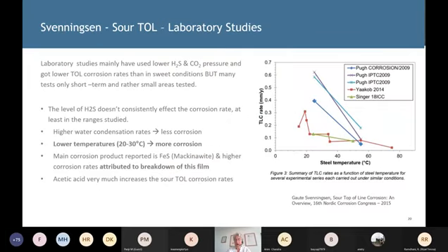I want to point out there's an area where we really don't know too much at all, and that's top-line corrosion in sour systems. Now, this paper by Svenningsson in 2015 is a key reference to bear in mind for this. He's done laboratory studies. What we need to mention is that they're all rather short term, and there have been small test areas in these cases. But the kind of effects that he's showing is that corrosion rates are surprisingly higher at lower temperatures. As you see on the right here, the water condensation rates don't particularly affect the results, but you tend to get even less corrosion if there's high water condensation.